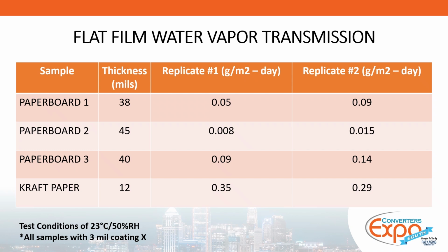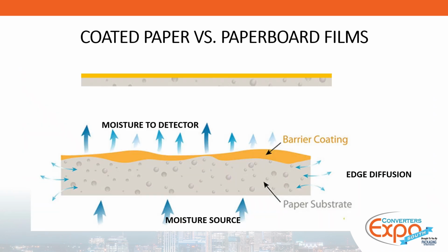So at the bottom there, you see their kraft paper product, which is their flagship product. And that was 12 mils thick with the coating and the substrate. And for that, we got pretty repeatable results for water vapor transmission rate. And then for all the three other ones that they were developing, you had much better barriers, much lower water vapor transmission. So why would this be the case? So it really goes back to the porosity of paper. So that's just additional surface area within the structure that creates like a honeycomb for the coating to actually move into. So then when that happens, you get inconsistent coating thicknesses, you get more defects, pinholes, things of that nature.